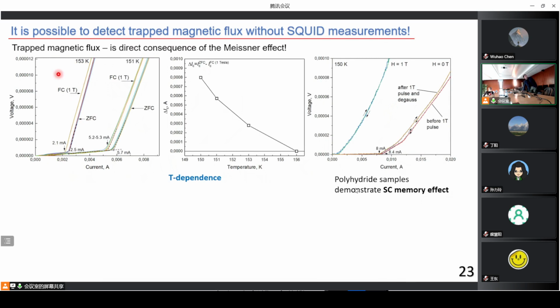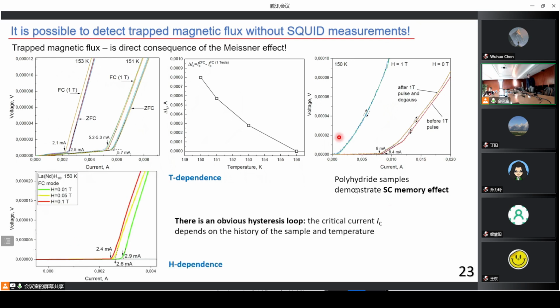And after that, we switched on the field, cooled down the sample, switched off the field, and the temperature was raised again to 153 kelvins or 151 kelvins, and we measured the critical current again. Several times, we were able to reproduce the fact that the critical current is now different, and the sample remembers what happened, remembers the field that was applied. So the polyhydrides definitely demonstrate the superconducting memory effect in these measurements.